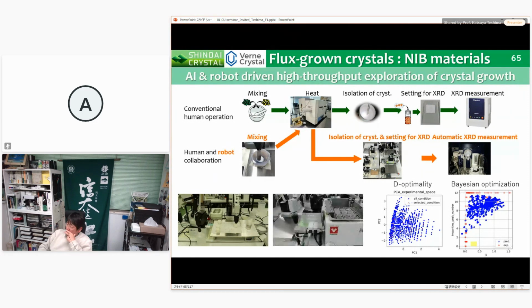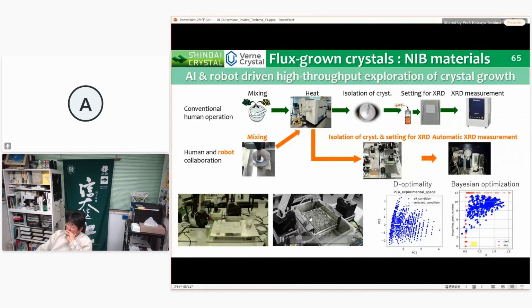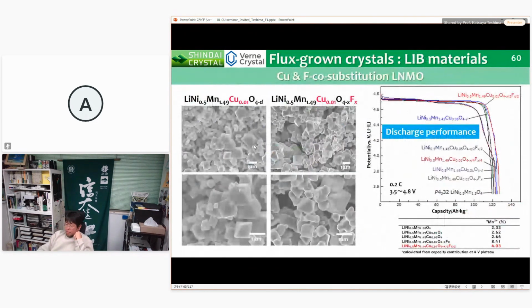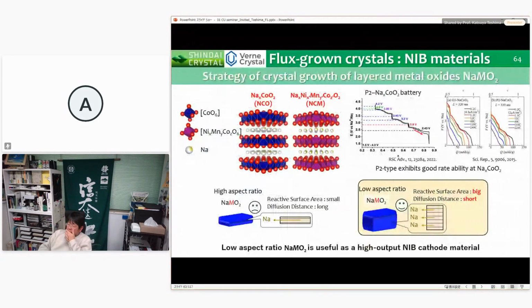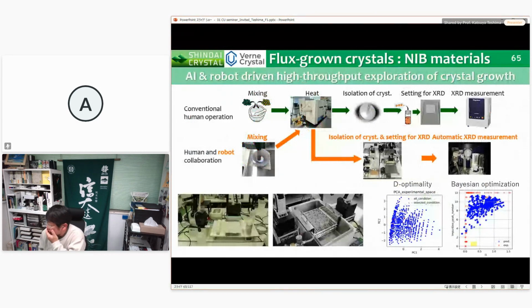As a result, the experiment speed was improved by about 10 times compared to manual labor. Furthermore, by incorporating data-driven experimental planning methods such as the D-optimality criteria and Bayesian optimization, we further improved the experimental efficiency by more than 6 times. As a result, we succeeded in developing low aspect ratio crystals in about 3 months of actual work per compound.